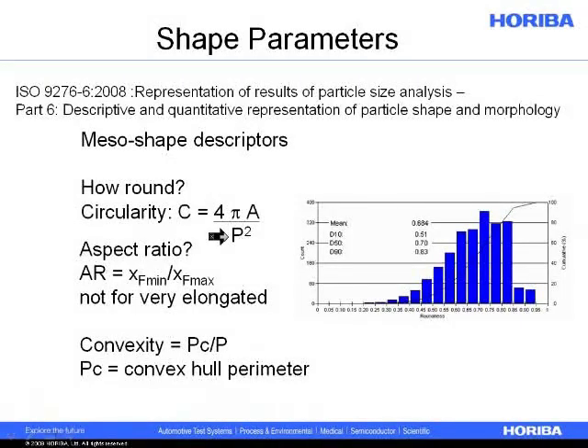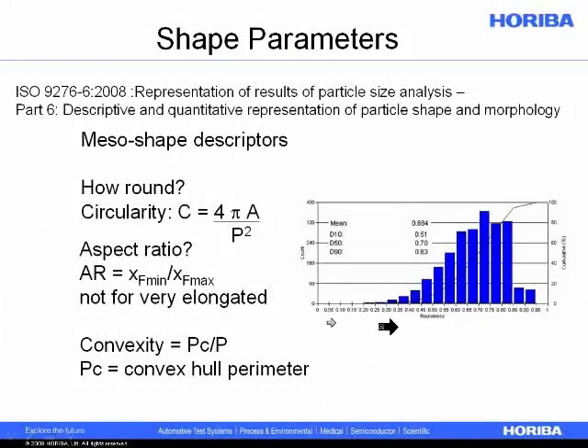There are quite a few shape parameters we could use to describe the glitter powder or any other powder. There's an ISO document showing a standardized way to calculate the shape of particles. For example, to know how round the particles are, we could use a circularity calculation, where A is the area and P is the perimeter. We could also use aspect ratio or convexity. For the glitter powder, the roundness distribution shows that roundness of one means a perfect sphere, and as that number decreases, particles are less round — so we could control not only the size but also the shape.